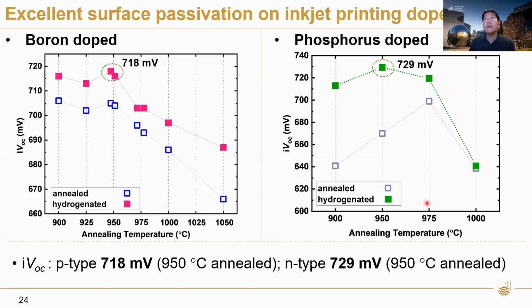So I'll briefly review the results that we've had. The figure on the left-hand side here plots the implied VOC, so that's the voltage. The higher the voltage, the better it is, against the annealing temperature. On the left, it's boron doped. On the right, it's phosphorus doped. In both cases, we're focused on the hydrogenated case. Hydrogenation is quite commonly done. It's almost built into the cell process and a bit hard to avoid, to be honest. After hydrogenation, we get about 718 millivolts for boron and about 729 millivolts with phosphorus.